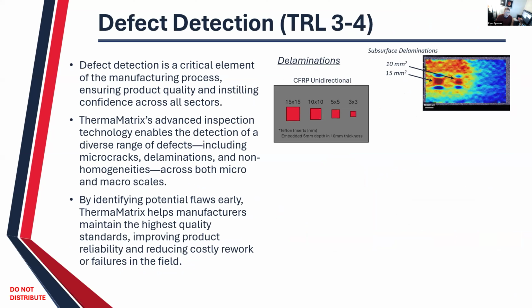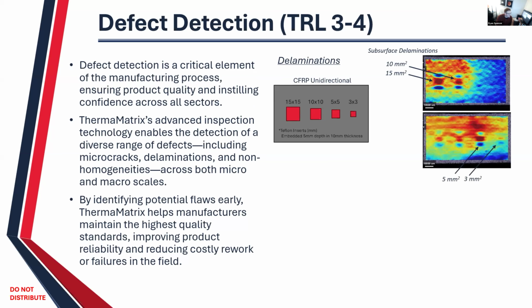Another case study is defect detection in general. We're looking to support delaminations, micro cracking, and porosity, but we have an example of monitoring delaminations with an array of simulated defects that are embedded in a CFRP unidirectional composite. You can see initially, with our heating methodology, we can monitor the 15 and 10 millimeter defects. And once we were able to improve our heating methodology, we can see a more full field of view inspection, actually capturing all the way down to 3 by 3 millimeter defects. And again, this is a rapid heating, rapid inspection to support that large inspection methodology.